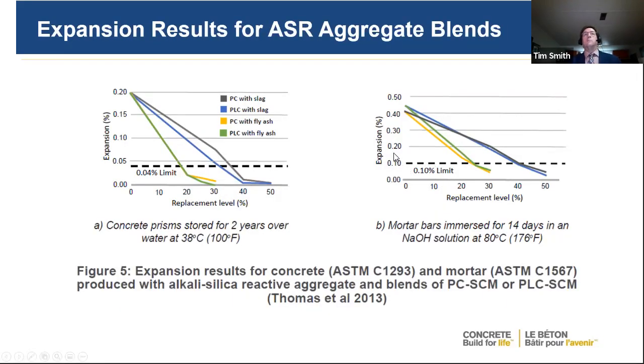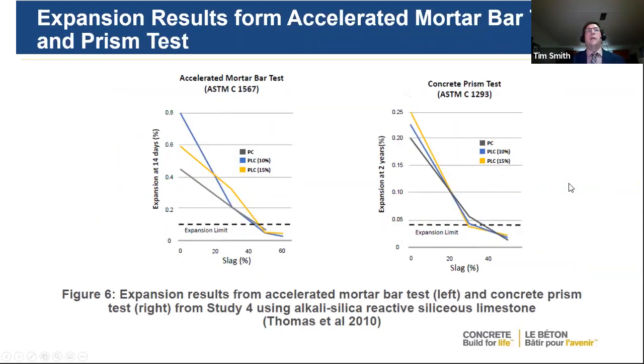If we want to look at expansion, same thing. The expansion results are very good. They're all below the limit that's required. So we see here that the limits are very low. The limits are very low in this area as well. And same thing if we're doing the accelerated mortar bar test or the prism test, the results are very similar. The two cements perform very well when it comes to expansion limits.